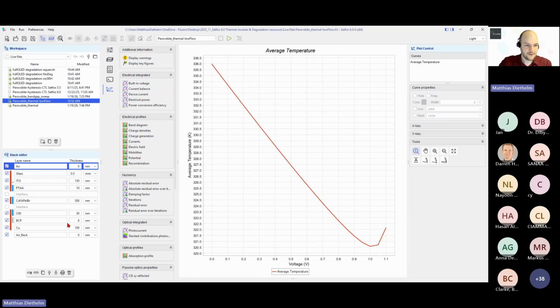Of course, you see here there's air on both sides. If you measure a device, typically you would have on one side a direct contact, so this changes the situation. But this situation would be representative for if you would put a device on contacts and it's somehow surrounded by air, not laying directly on the heating plate, for example, or some other material.